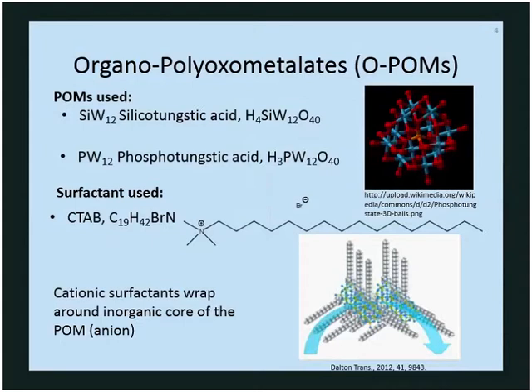So in this Keggin structure, the middle atom, the orange one seen in the structure, is the inorganic core. And then it's surrounded by oxygen atoms in red here, bonded to the transition metal tungsten. And then that is anionic. And so the CTAB surfactant is organic and it is cationic, which in the synthesis wraps around the inorganic core of the polyoxometalate anion.